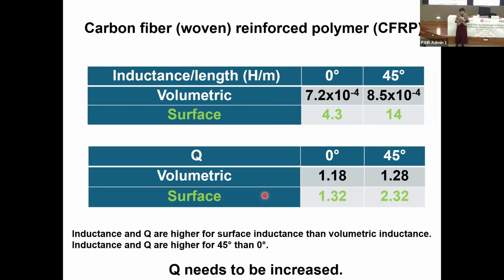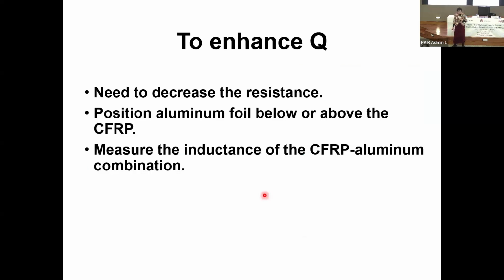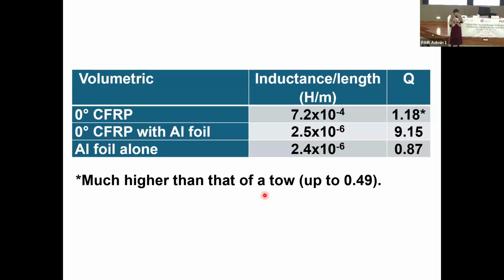So the surface inductance is very interesting. But the Q factor is still not good enough. It's just 2.3. That's not good enough. So how can we increase the Q? Well, we need to decrease the resistance. And we have a simple way to decrease the resistance, and that's simply position an aluminum foil below or above the CFRP and measure the inductance of the CFRP aluminum combination. You can see that with the aluminum foil, the Q goes much higher, 9.15. Without the aluminum foil, it's 1.18.